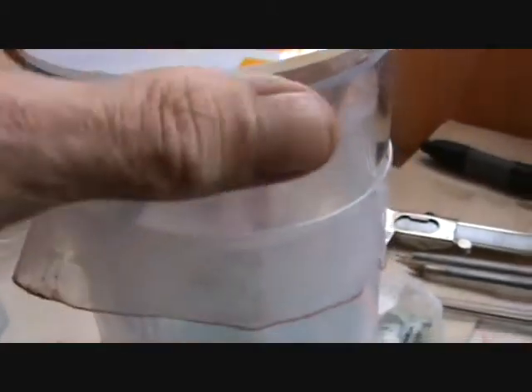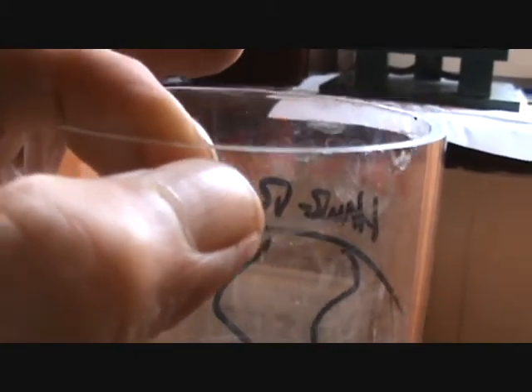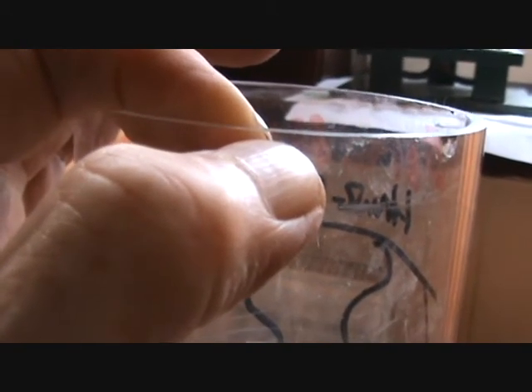Now, when you get these tubes, don't remove the stuff off them. Just peel it back slightly. You don't really want to be removing it because it will stop any scratches. But when you peel it back, my advice to you is to check that you've not got any wee laminar cracks in here. Because if you've got even a millimeter crack in there, you're either going to live with it or when you're building later on, adjust for it. You would be forever trying to get rid of a millimeter crack there. And just check that you've not got any major cracks running down the inside lines or anything. But I would definitely check these edges before you start working on it. Send it back to the manufacturer and get it replaced. These ones you'll deal with because these are just saw cut marks. And this is where we're going to get ready first to get a nice flat finish so we can weld on.